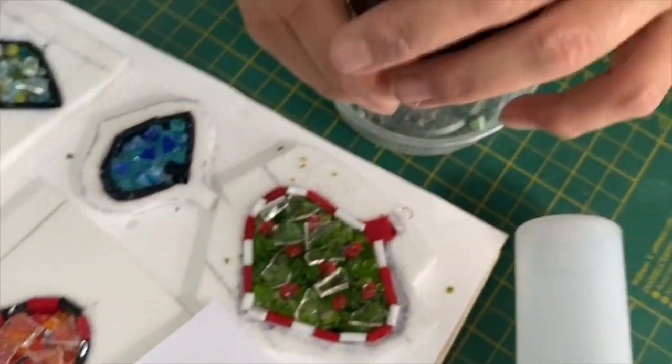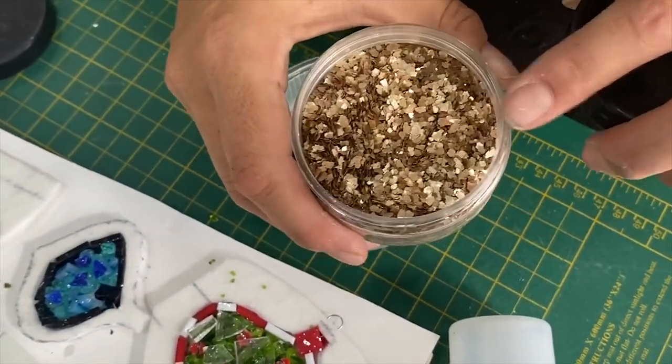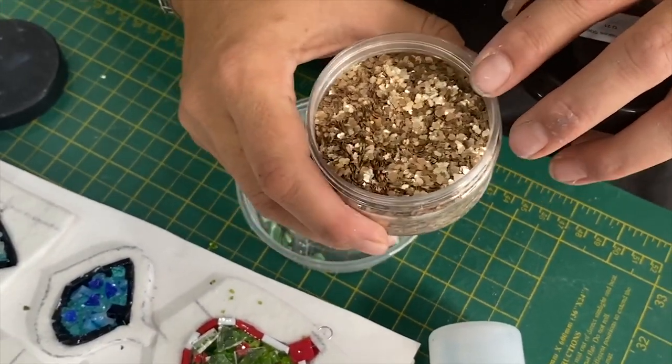I got these from Warm Glass a long time ago. If you're going to use something like this, these kind of inclusions, be wary. I've looked at them under the polarizing filters to look at compatibility after I've done them, and they really flare. So put too many of these in your work at your own risk. They may well make it break.